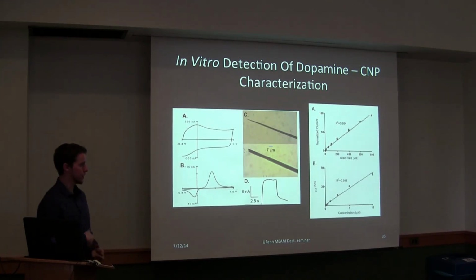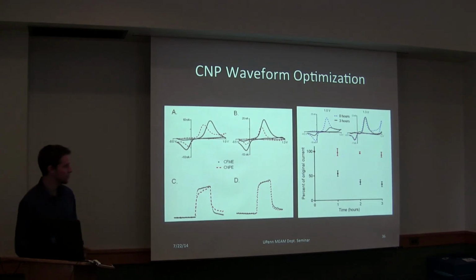So that's important for converting between peak current and concentration if you're trying to measure concentrations. They did some waveform optimization, basically just looking at two different ranges of potential scanning, going up to 1 volt or up to 1.3 volts. They showed that 1.3 is both more stable over time and has a time signature that's very similar to carbon fiber microelectrodes. So this is just comparing the black, which is carbon fiber, and the red, which is the CNP. We also noticed that with the CNP you get faster kinetics, which is shown by the peaks being closer together.